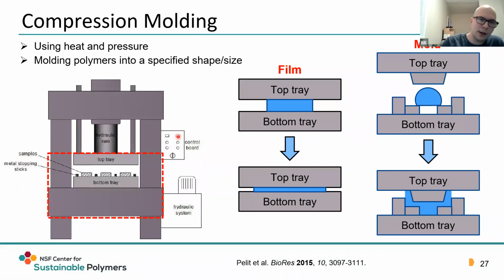So one way to mold a polymer film to an irregular substrate is with compression molding. This allows you to access either kind of thicker films from the melt exclusively. There is no need for a solution or a solvent. It does allow you to get some basic irregular shapes as well. The main parameters you have here controlling your sample properties are your heat and pressure, and then your hold time and some of your cooling characteristics.